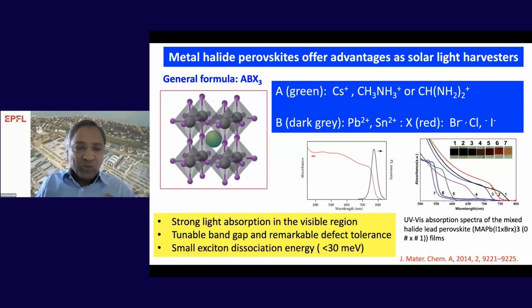The second interesting property of this material is a tunable band gap. So you can change the absorption properties of these materials by changing the halide composition. So if you look at this diagram, which is taken from the reference below, perovskite absorbs up to 820 nanometers. As you increase the bromide percentage in the perovskite composition, you can see the widening of the band gap. So the absorption moves from 820 nanometers to 550 nanometers. So this way, you have plenty of opportunities to tune the material properties.